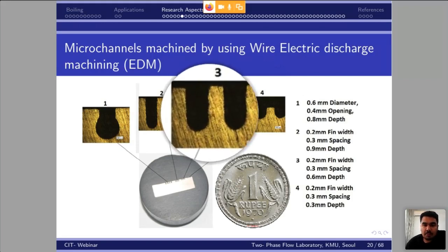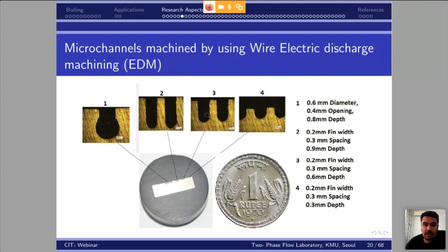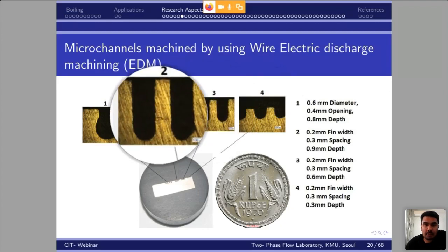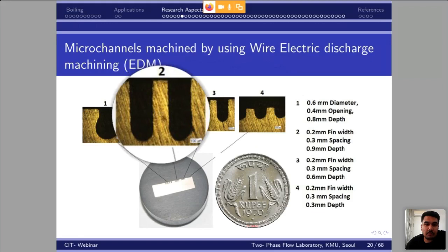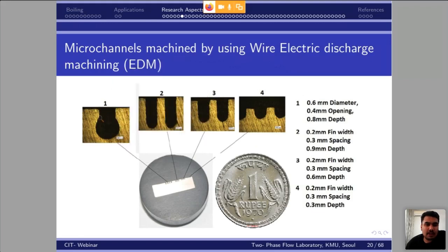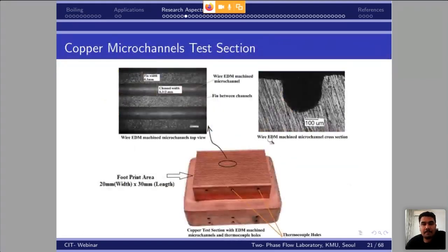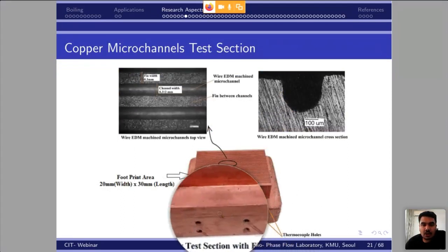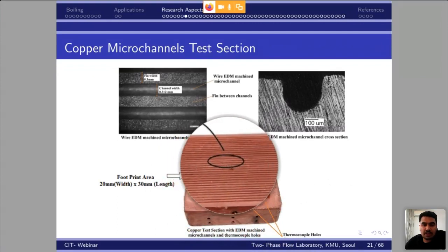This one is 0.3 mm spacing with 0.6 mm depth. This is 0.9 mm depth with 0.2 mm fin width and 0.3 mm spacing. This is another type of shape. We will call it a reentrant channel, and you can see some different shape channels here. So this is a channel that was machined using EDM, electric discharge machining. This is just shown as an application part, how it looks like. This is the machined channel. This is the heat sink. You can see how the channel is machined in copper.